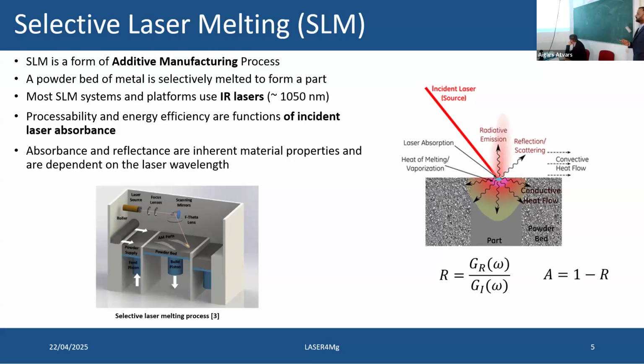Most of these systems use infrared lasers, at about 1050 nanometers. The processability and the energy efficiency, meaning how effectively the energy we put into the system is used, is a function of the laser absorbance. If the metal doesn't absorb enough of the laser, then the efficiency goes down. Both of these properties depend on the laser wavelength. The absorbance A and the reflectance are related by this equation right there.